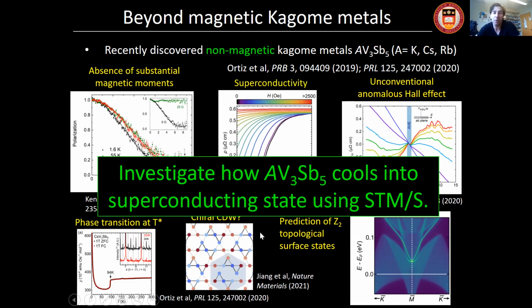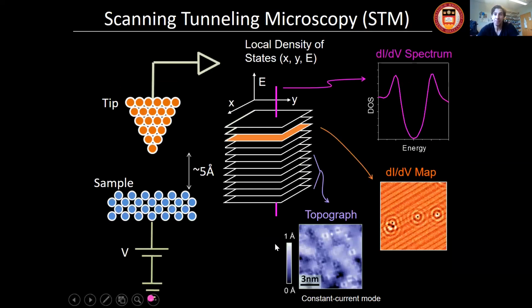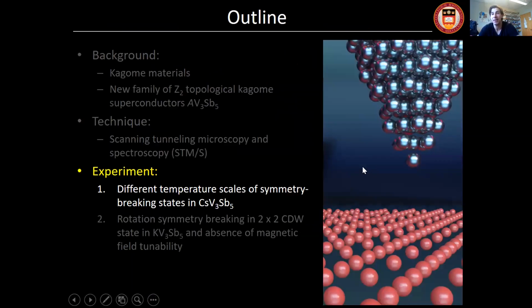And in our work, we basically wanted to investigate using STM how this system cools into the superconducting state. So we're going to use variable temperature STM to really visualize some of these interesting phenomena and actually find something that was not uncovered using these bulk probes. Okay, so the technique that we use is STM. I'm not going to explain anything here, but basically we're going to use topographies, dI/dV maps and dI/dV spectra to complementarily look at different aspects of this system.